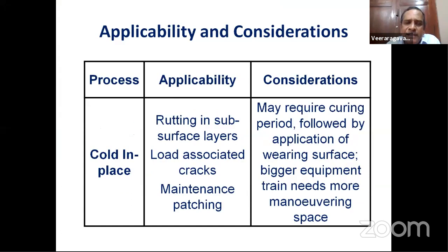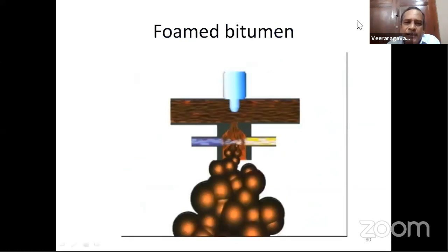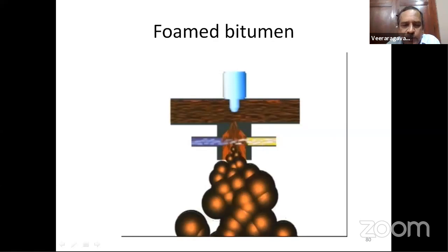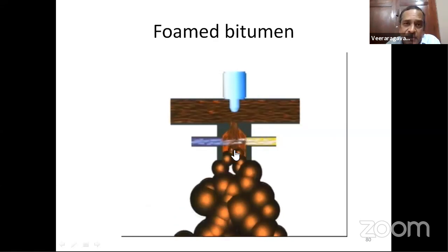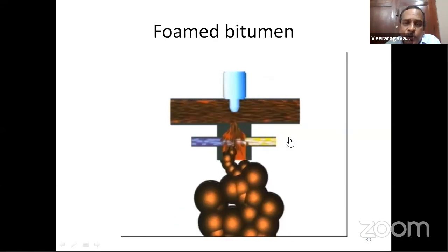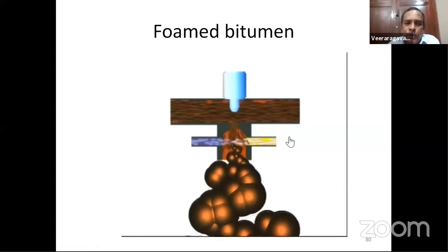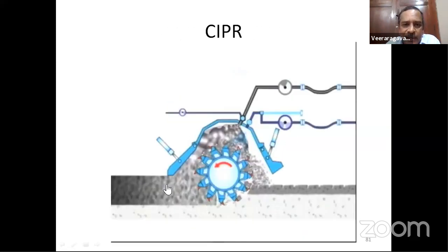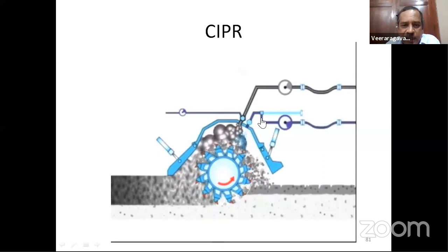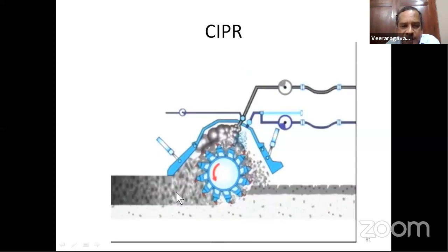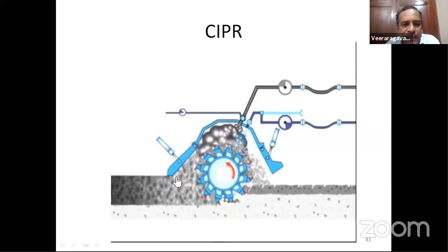Cold in-place recycling can also be done, wherein you can mill the bituminous layer as well as the base course, add foam bitumen and relay it back as an excellent binder course. What I try to do is that in hot bitumen, I inject water, I inject air. The volume of bitumen increases by 14 to 17 times. So when I want to construct a road, I mill the material, I inject the foam bitumen, it tries to mix the material together and it can be laid.